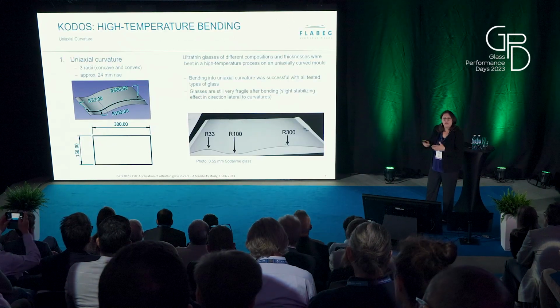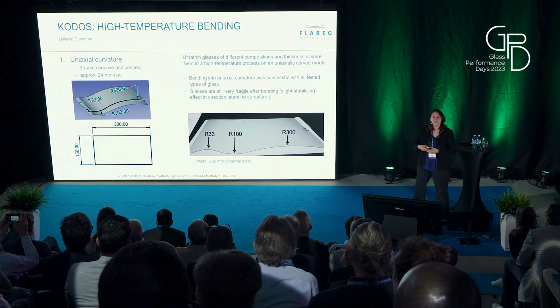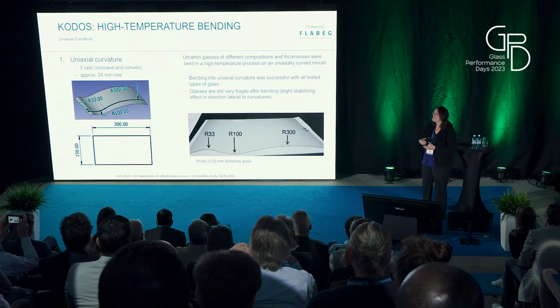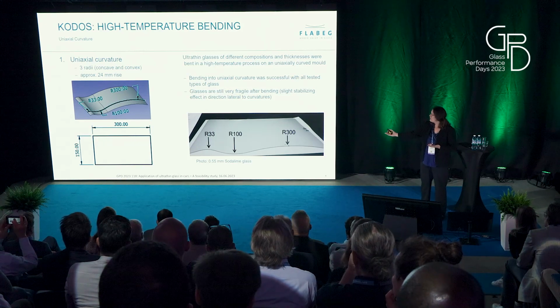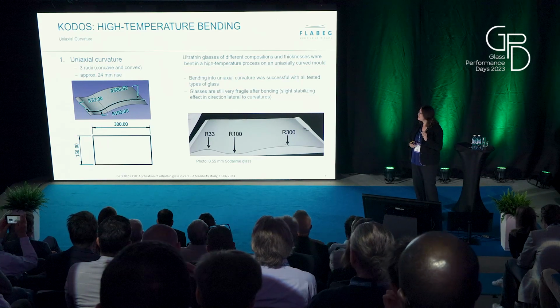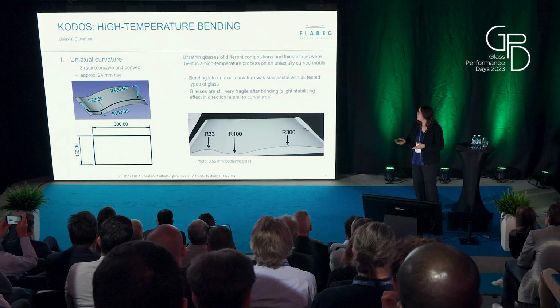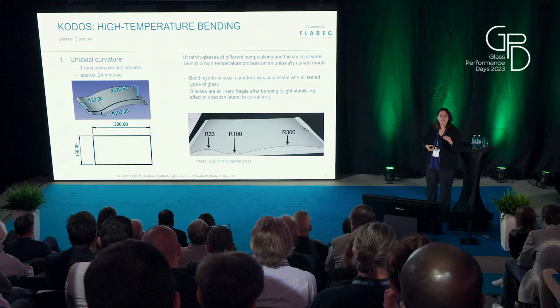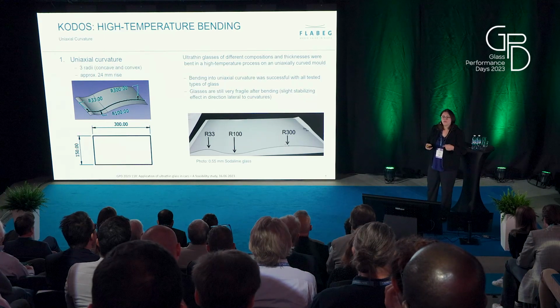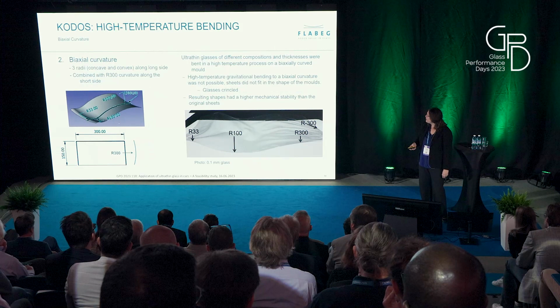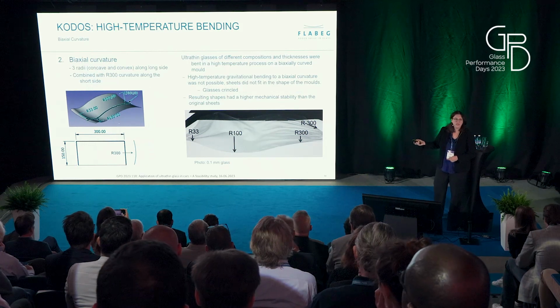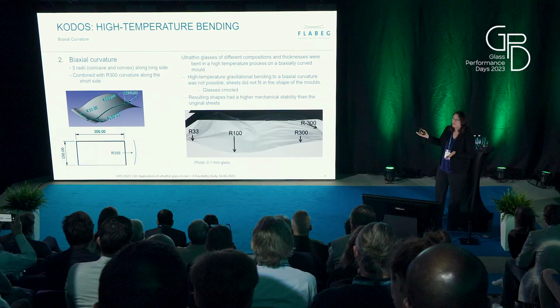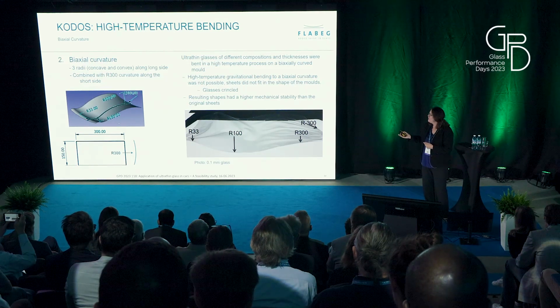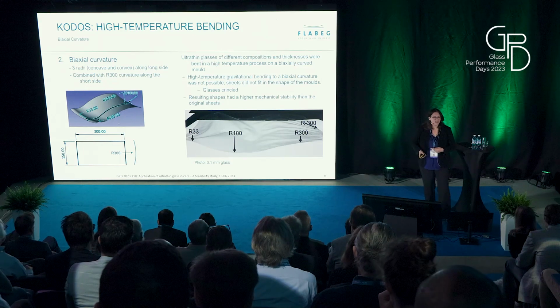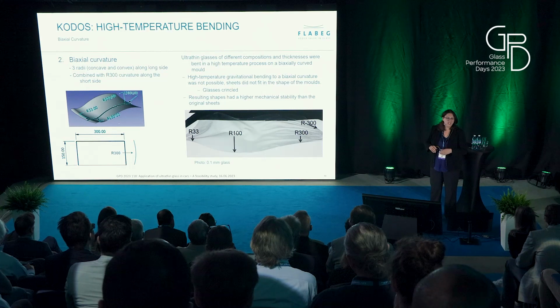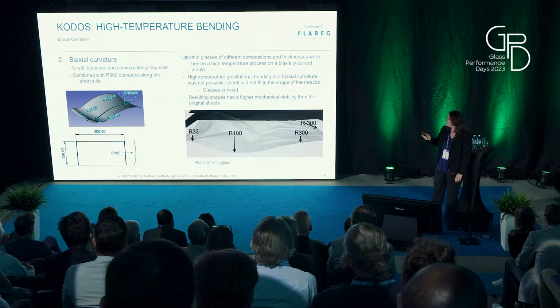So we talked a lot about cold bending, but what about hot bending? And our partner Flabeg did some hot bending experiments for all these different glass types, different thicknesses. What you see here is a 0.55 millimeter thick soda lime glass with different curvatures, and it worked quite well. So this is working as long as it is just bending over one axis. But if you want to get really three-dimensional, we end up here. You see some wrinkles, and at least with gravity bending, with the existing tools, it's not surviving. I mean, it's not helping that the glass gets stiffer if you cannot do any lamination with such a wrinkled something. So we just discarded the idea of getting three-dimensional forms in that dimension.